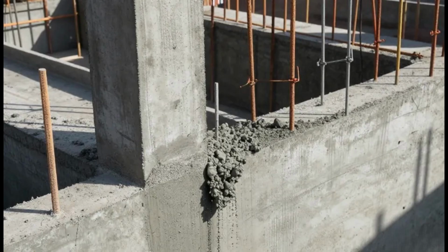The first cylinder failed at a compressive strength of 31.4 megapascals. The second failed at 32.1 megapascals. The average was 31.75 megapascals. The specified characteristic strength for a C25/30 concrete on 150 mm cylinders was 30 megapascals. Both cylinders exceeded this value. The concrete complied. The report was issued and sent. Eno received it, read the numbers and filed it.